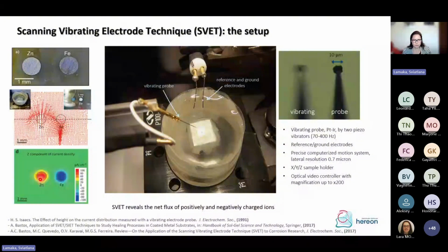And we grow a layer of platinum black. The diameter of the probe is between 10 to maybe 20 micrometers, and vibration amplitude is also between 10 to 20, maybe 30 micrometers, but not more than that. The vibrating probe of SVET, during this vibration between 2 points near the metal surface, measures the potential difference that is formed in solution due to the ionic fluxes produced on the sample surface by chemical or electrochemical reaction. The relationship between this measured potential difference and the associated current density is established by calibration.